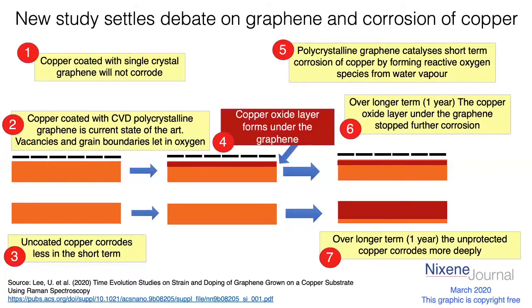So this sort of unpacks the mystery, which is, yes, copper does corrode initially with polycrystalline graphene on the surface, but once that corrosion has formed, it forms a barrier and stops the corrosion forevermore, whereas unprotected copper will actually carry on corroding. Do you think that sort of explains and solves the mystery, Debbie? Well, it sounds like it to me. Graphene's supposed to protect copper, and it does, but only if it's single crystal graphene, or it does provide a thin layer of the copper oxide and then protects it from that point.